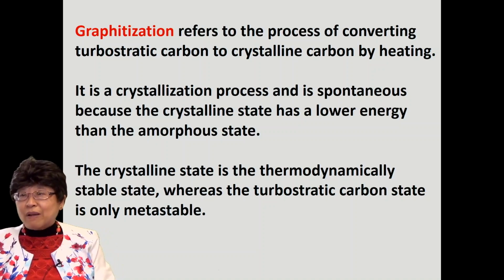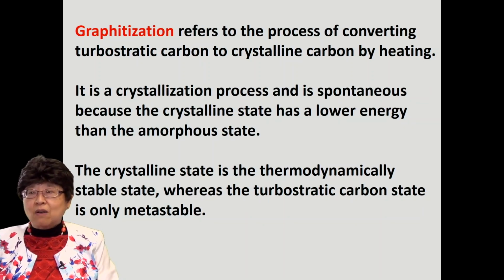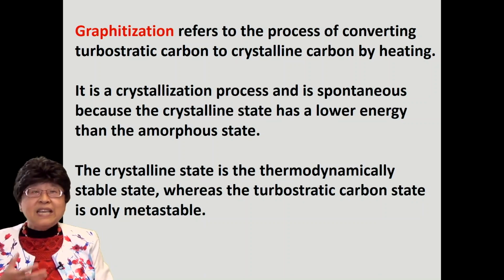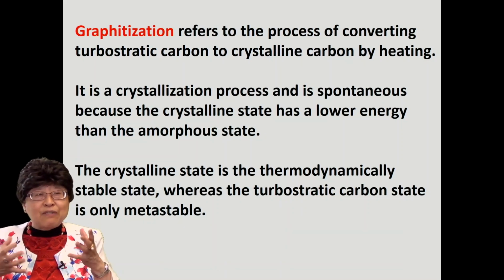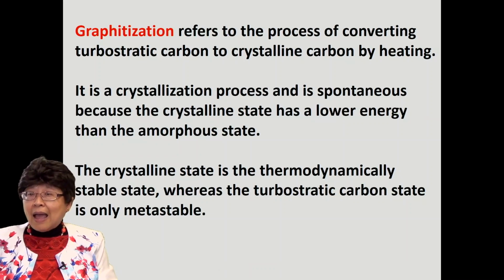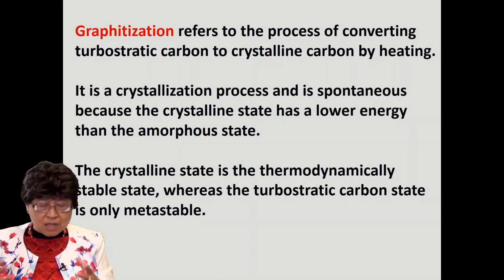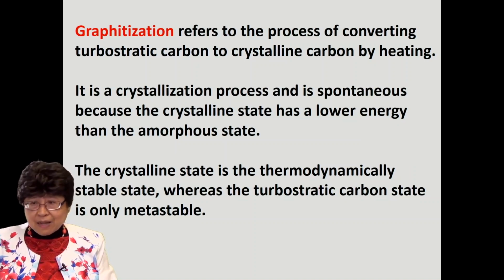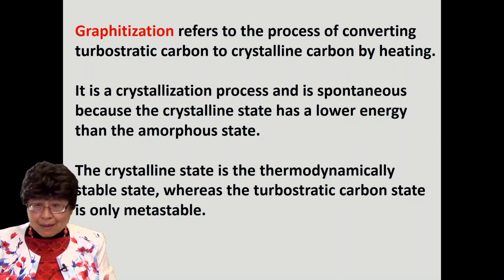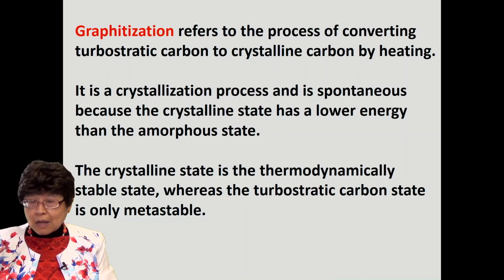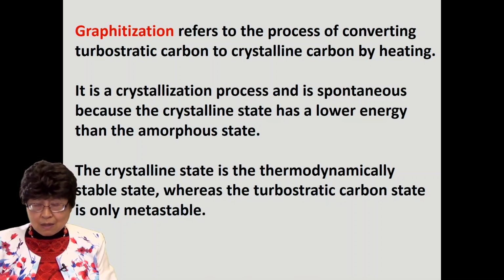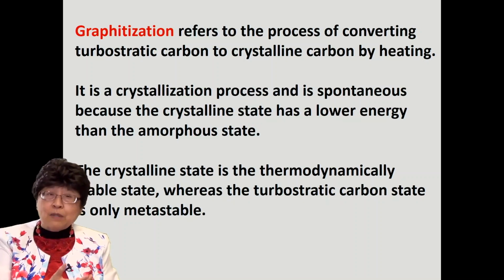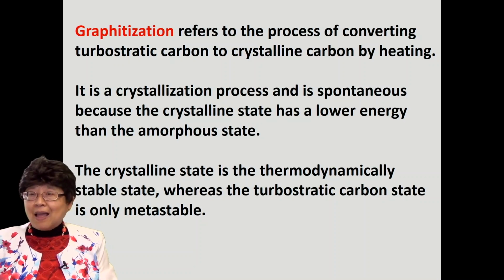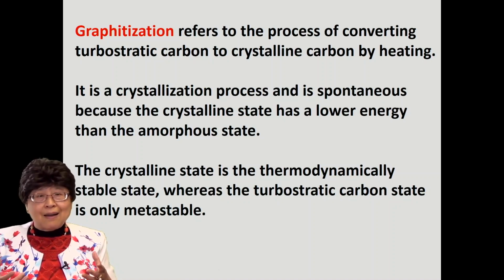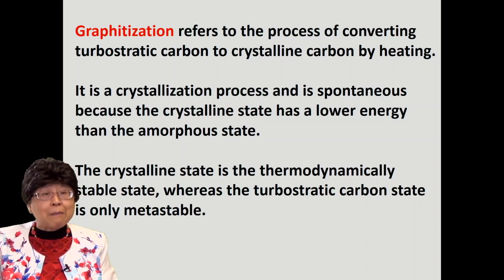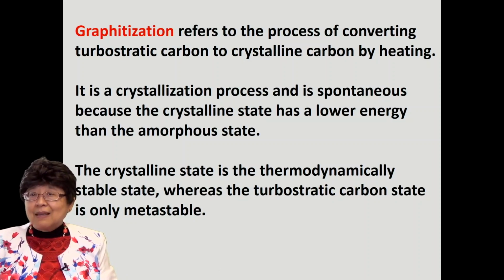Now, there is a process called graphitization, which can convert turbostratic carbon to crystalline graphite, and that's simply heating to a high enough temperature so that the atoms have enough thermal energy to move without melting. Okay? And they would automatically move so as to become more crystalline, okay? Converting the turbostratic carbon to graphite. And this conversion occurs automatically upon heating to enough temperature because the ideal graphite is the thermodynamically stable state, whereas the turbostratic carbon is not thermodynamically stable. We say it's metastable. Okay? And so if you give it enough thermal energy, anything metastable would want to change to the thermodynamically stable counterpart. And that's what's happening in graphitization.